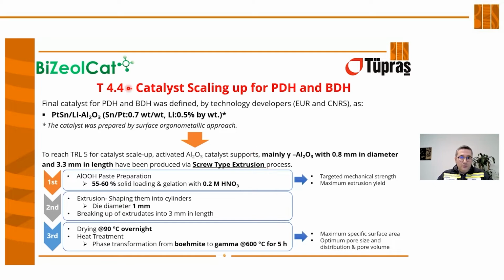So the final catalyst for PDH and BDH was defined in work package 2 by the technology developers, Eurocat and CNRS. This is the lithium doped gamma alumina, deposited with platinum and tin. The ratio of tin over platinum is 0.7, and lithium is nearly 0.5 weight percent.